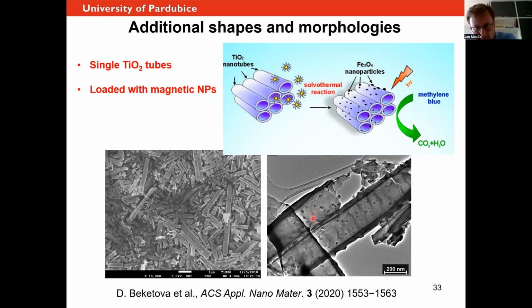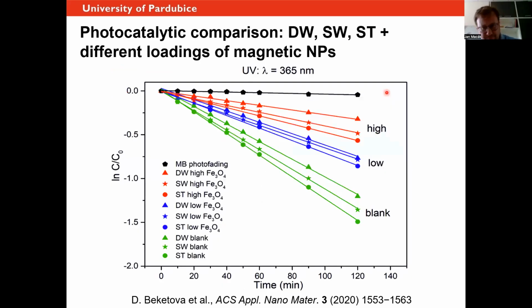We managed that. As you can see here in the TEM, we have these nice superparamagnetic particles, which are on the scale of 10 nanometers. And this gives you incredible power of having high surface area TiO2 in the nanotubular shape on one hand side. On the other hand side, it gives you the magnetic force. So you can actually move these powders in a magnetic field very easily. I just want to say that we, at first glance, tested it for photocatalysis with the single tube, double wall, and so on. And we investigated something which at the end was not surprising.